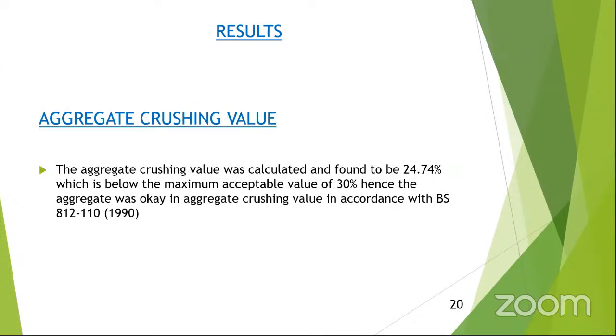The aggregate crushing value we calculated and found to be 24.74%, which is below the maximum acceptable value of 30%. Hence, the aggregate was okay in aggregate crushing value in accordance with BS 812/110/1990.